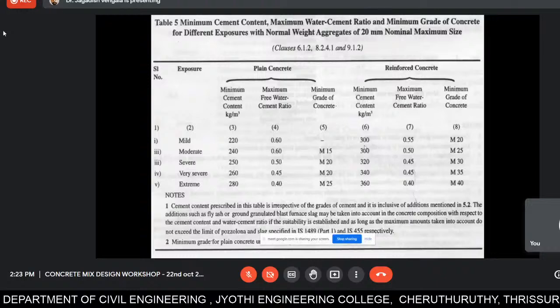The maximum cement content we can go for, as per IS 456, is 450 kg per cubic meter. IS allows you to use mineral admixtures in replacement of cement as long as you get the required grade of concrete, whether it is fly ash or GGBS or any other mineral admixture. And also you can reduce the water cement ratio and get the required strength. At the same time, you can get the slump by adding chemical admixtures.